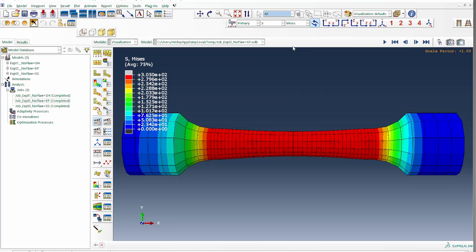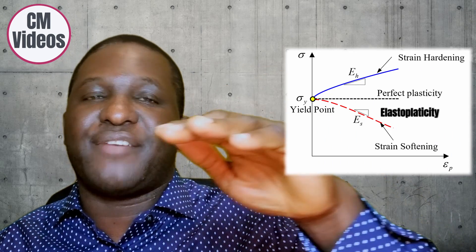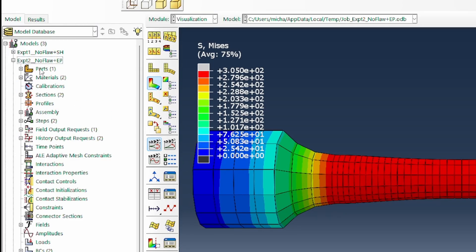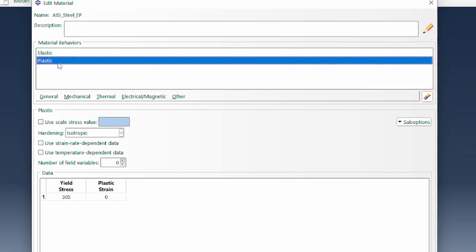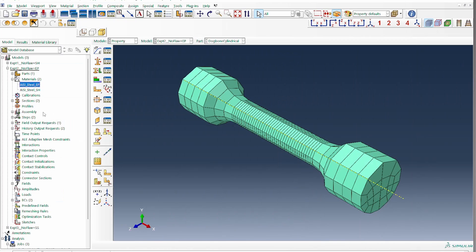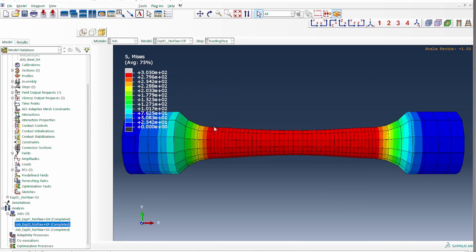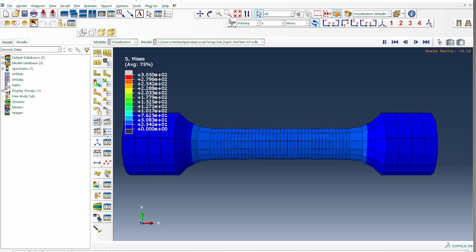In the second experiment, there is also no flaw in the specimen, but it has an elastoplastic material model: stress builds up to yield, and after yield the material stays constant — neither strain hardening nor strain softening. For necking to occur, we'd expect some compromise on strain hardening compared to increasing strain. The result shows no necking, because there is no flaw and no strain softening or significant strain hardening compromise. Both requirements to drive necking are absent.